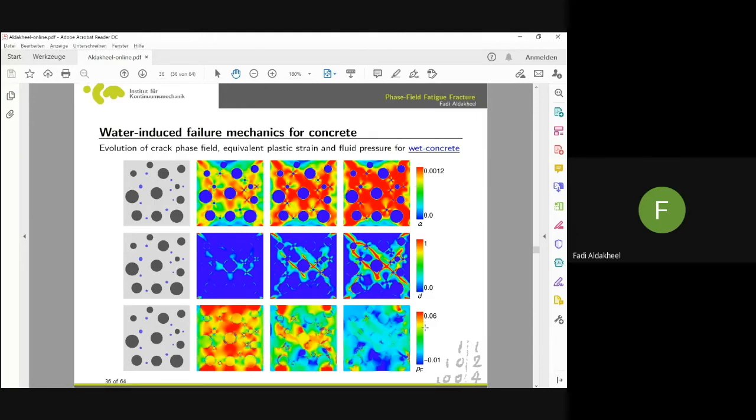So it is clear that if you have pores filled with water, and you compress the specimen, the water will be compressed till some limit, like it will be accumulated, as you can see in this red area. And here, let's say the hardening, or the plasticity, will be in those areas. At some limit, when the fracture takes place, that means it goes to 1, you have free space now. You have a crack open. When the crack opens, the water flows out from this pore to another place, and the pressure drops, right? It has to drop and go to the other place. You still continue compression, and the pressure accumulates till the crack surface comes to this area, the crack propagates, pressure drops, and so on, right? So one can think about it like that. This is a kind of tricky porous media. This is how it happened here till final failure.